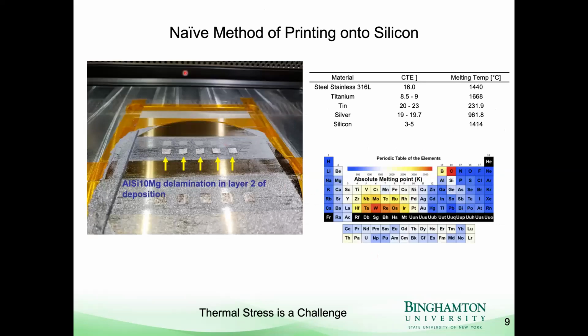Now, what if you just try to print metal directly onto silicon? Well, this is kind of a naive attempt, and you see that there's very poor bonding. This was printing aluminum onto silicon. This is the silicon wafer here, and you can see at the corners that these squares have delaminated. The reason for this is that aluminum melts at a relatively high temperature, and it also has a coefficient of thermal expansion mismatch with the silicon. Most metals have much higher thermal expansion than silicon does. So these two things make it hard to print metals onto silicon.